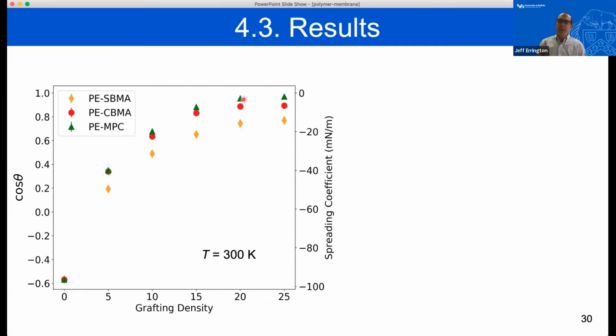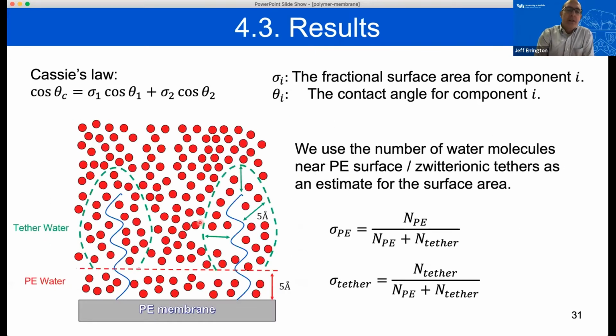So at the end of this, one of the things that we were interested in was, okay, so we've gone through the calculations to determine the contact angle and how that evolves with these different grafting densities. And we wanted to say, okay, well, instead of having to do all the calculations, is there a way to perhaps estimate or predict, based upon other information, what the wetting behavior of one of these systems would be with some arbitrary number of tethers grafted to the surface? So what we looked at was the possibility of applying ideas associated with Cassie's law in order to make such a prediction.